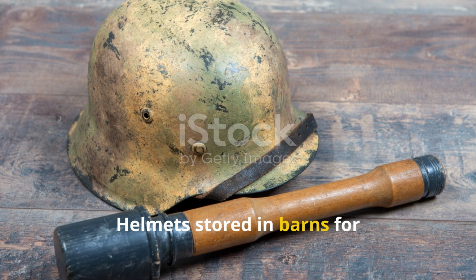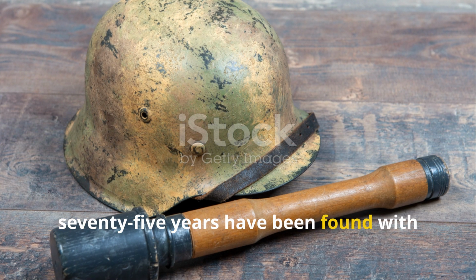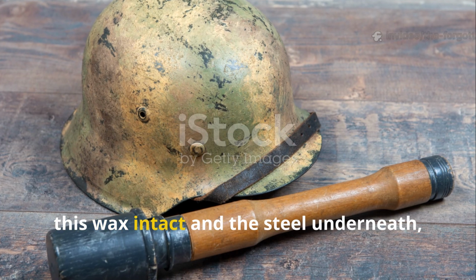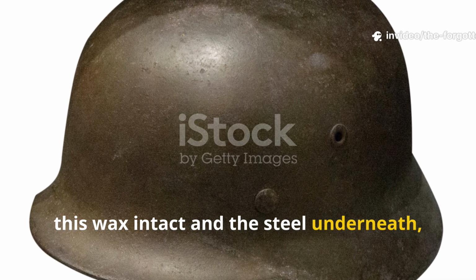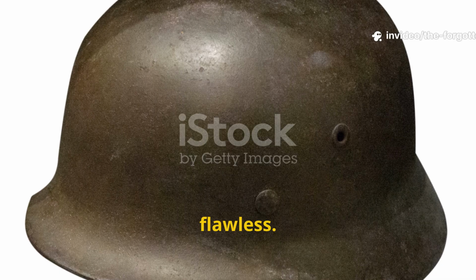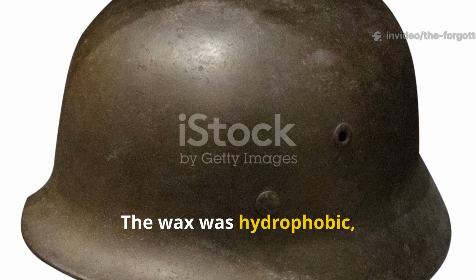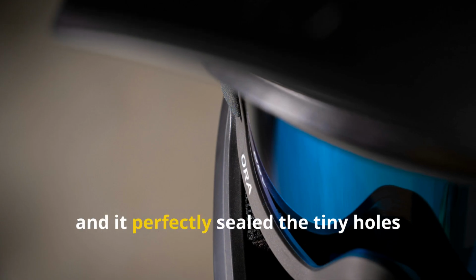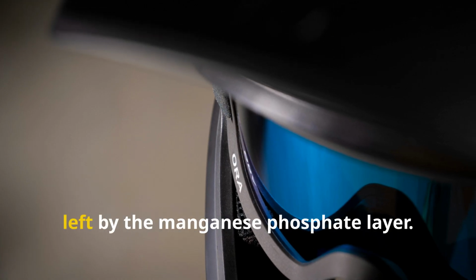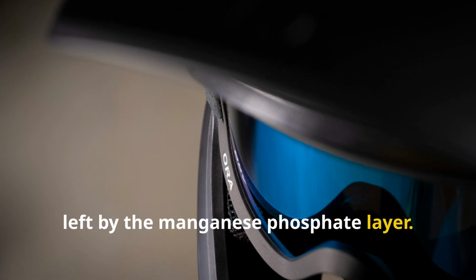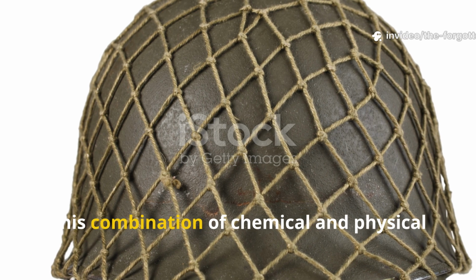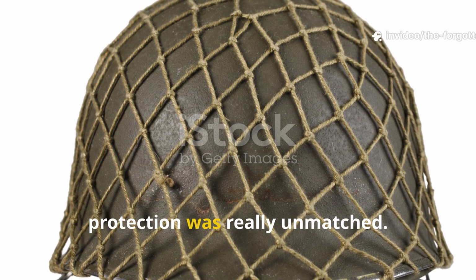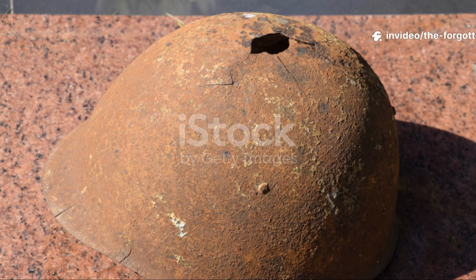Helmets stored in barns for 75 years have been found with this wax intact and the steel underneath, well, flawless. The wax was hydrophobic, chemically stable, and it perfectly sealed the tiny holes left by the manganese phosphate layer. This combination of chemical and physical protection was really unmatched.